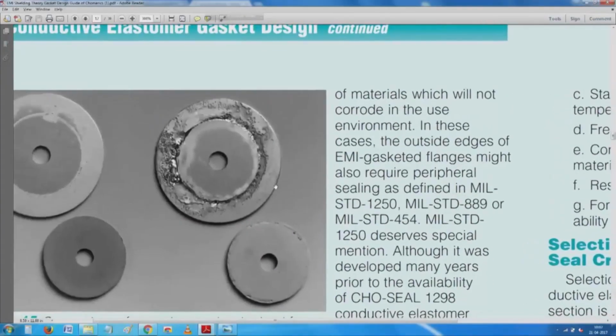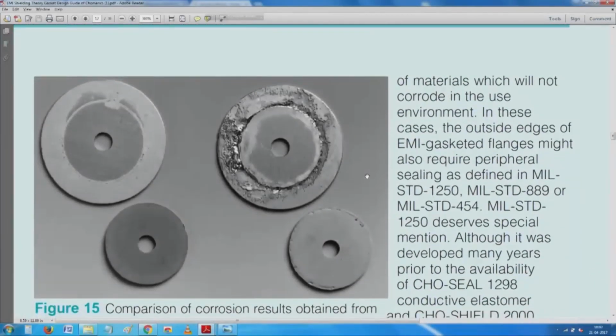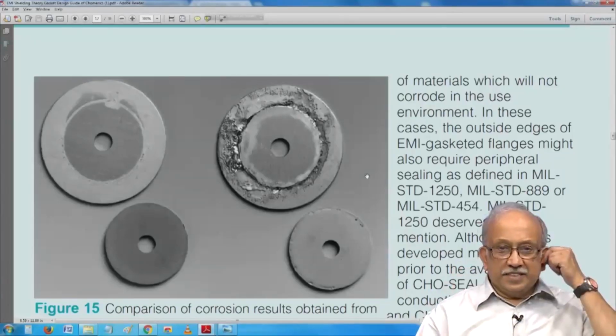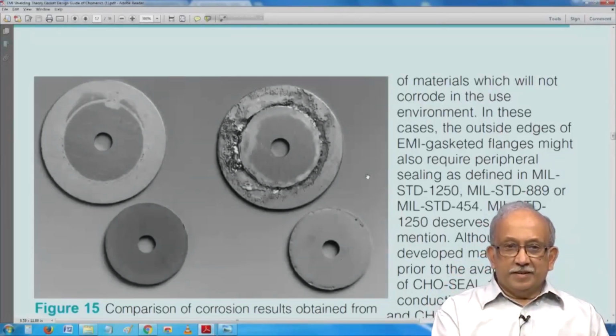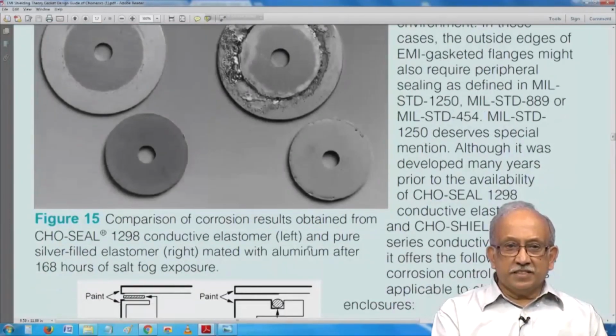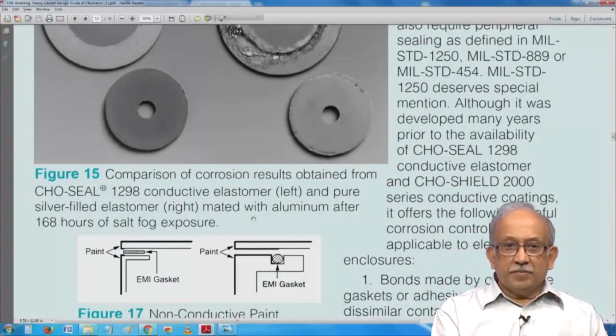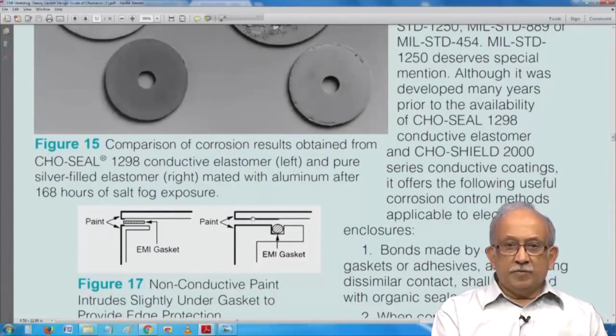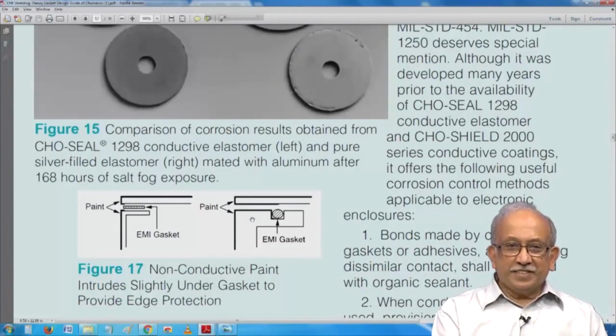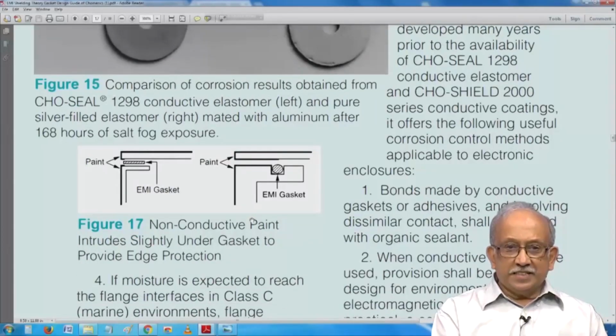And then here pictures are shown of the test results. You see around the edge where it is exposed to the atmosphere and it can get all the necessary moisture, it has corroded all around at the edge. The center does not seem to be so bad. Comparison of corrosion from Cho-Seal and pure silver filled elastomer with aluminum. This, well, I will not say it is not real, it is individual case specific.